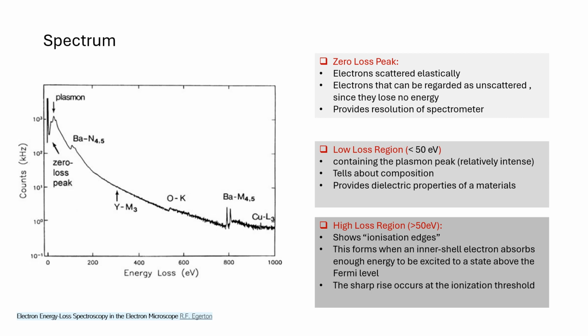So to analyze a spectra is one of the most important things to do. Now the EELS spectrum has three prominent regions. First is the zero loss peak. This is an intense sharp peak and it represents electrons which have not been scattered in the specimen or which have been elastically scattered via interacting with the atomic nuclei. The width of this peak is around 0.2 to 2 electron volt, and the FWHM, or full width at half maxima, tells us about the resolution of the spectrometer.